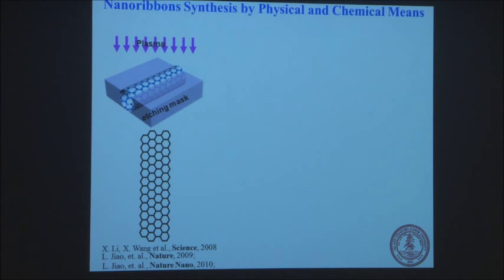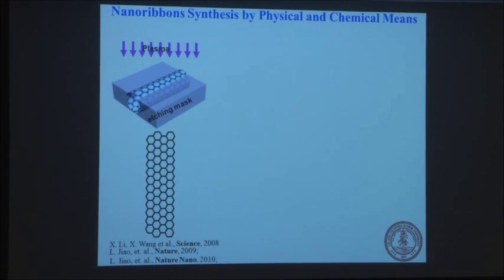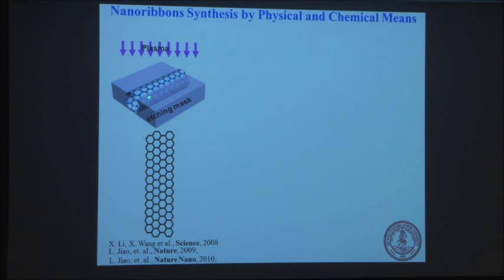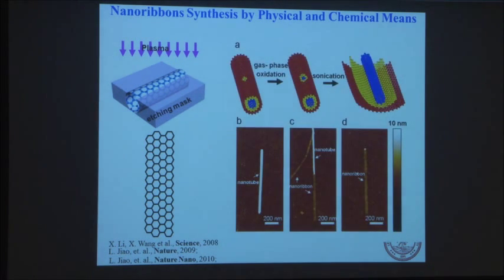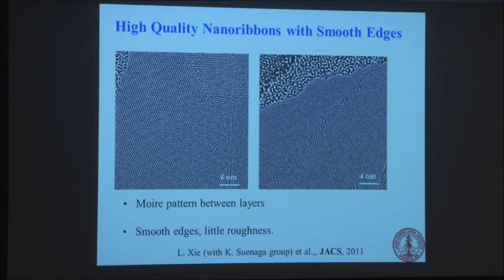The way we did it at the time was we coat a tube with a polymer photoresist, and then you peel it off from the substrate, then the side of the tube that's touching the substrate is not coated by the polymer. So you can just do a plasma etching, so that this row of atoms is removed. So this works really well and gave us some ribbons. Lately, we've been trying even simpler methods like sonication. You can sonicate nanotubes, and sometimes you actually get ribbons. So it's a very simple process, but there are some details you have to control. And we do things like high-resolution imaging, and we look at how good the edges are, whether these are potentially good for things predicted by theory. So in this case, you see that the edges are pretty good. I don't think it's atomically smooth, but very smooth.